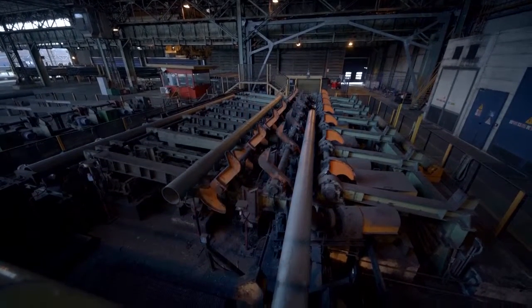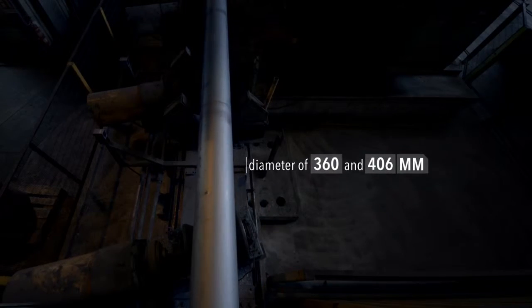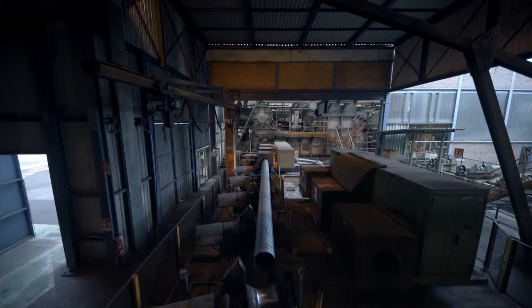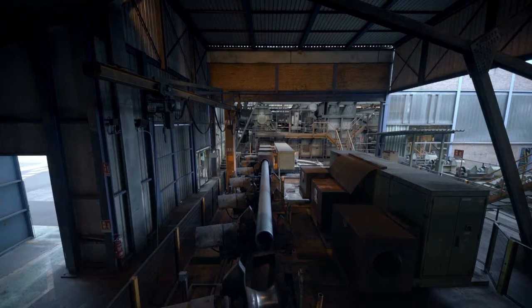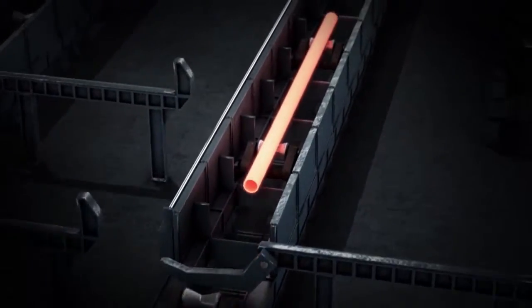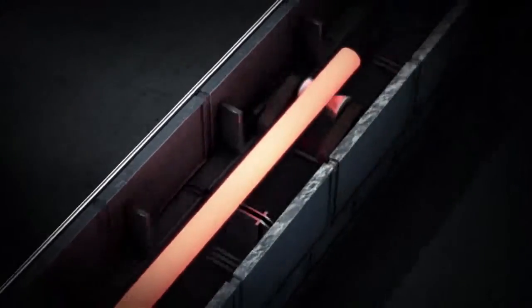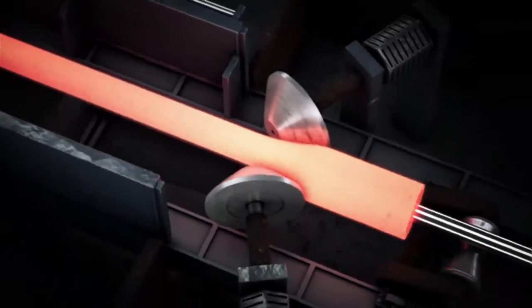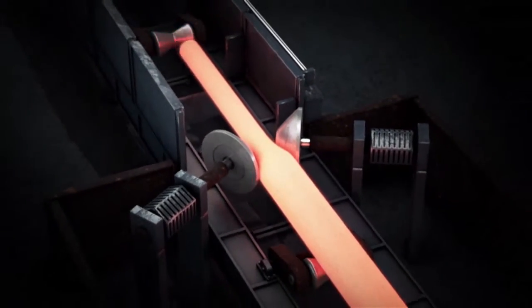Mother pipes with an external diameter of 360 and 406 millimeters are used to form large diameter pipes. After heating, mother pipes are expanded through a cross-rolling mill on a taper plug. The reduction in thickness is compensated by the increase in the tube diameter.